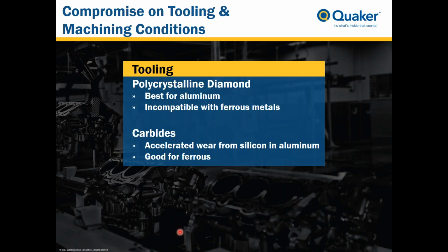Unfortunately, they're not compatible with ferrous materials because of the degradation of the tool material, the diamond, as it solvates up into the ferrous component at higher temperatures. Typically, what you need to do is run with another material, and quite often in bimetal operations, carbide tooling is used. Carbides are okay for aluminum, and they're usable, but there is higher wear that results from the high silicon in the aluminum on the carbide, and it's okay for ferrous as well. So you can see that while there are optimum tool materials for each of the metals in a bimetal operation, you usually settle on a compromise.